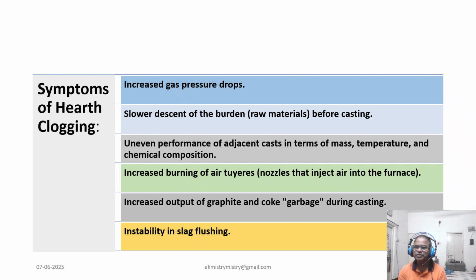Now, what are the symptoms of hearth clogging? Here is how you know your hearth is clogging. You'll notice a sudden increase in gas pressure drops, which is a very important symptom. The burden descent slows before tapping. Cast to cast variation in weight, temperature, and composition becomes a frequent phenomenon.